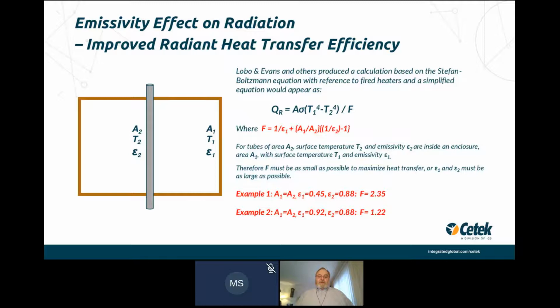F is the interesting thing. We have to keep that factor as low as possible to maximize the radiant heat passing from the wall to the tubes. And you can see underneath, F is equal to, again, another equation based on surface areas and emissivities. And if you scan down to the bottom, the first example would be for a ceramic fiber lined unit, where E1 is 0.45, E2, the surface emissivity of the tubes, is 0.88. And we're assuming that the surface area of the refractory and the tubes is the same, just for simplicity. Here, the factor would be 2.35.